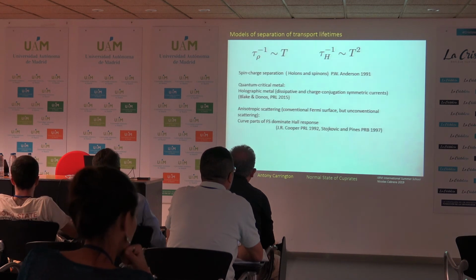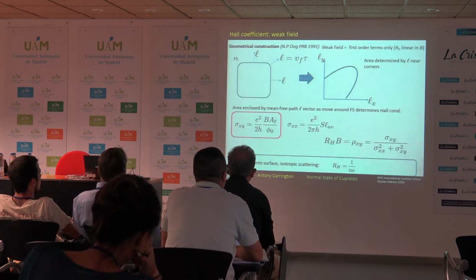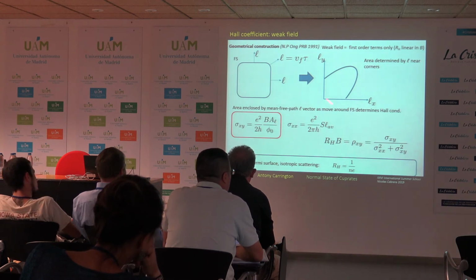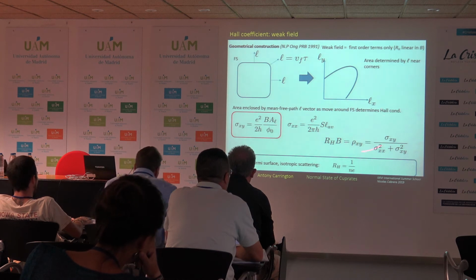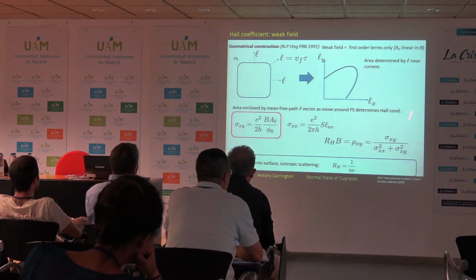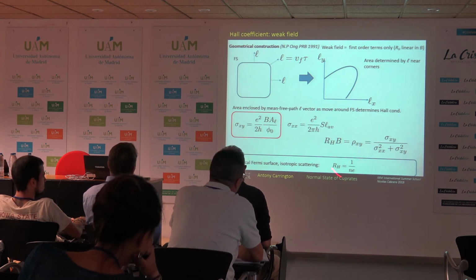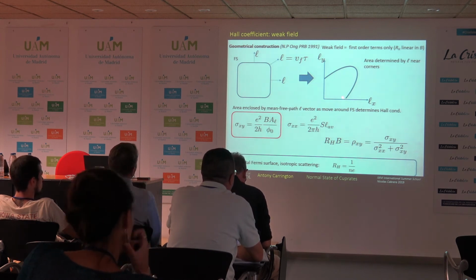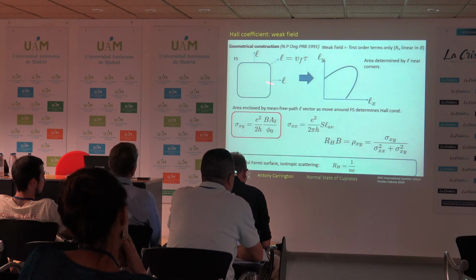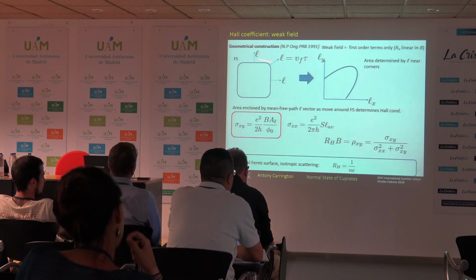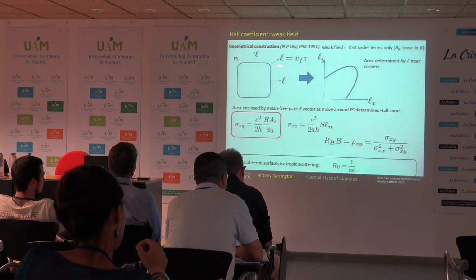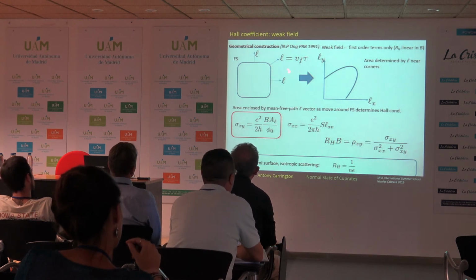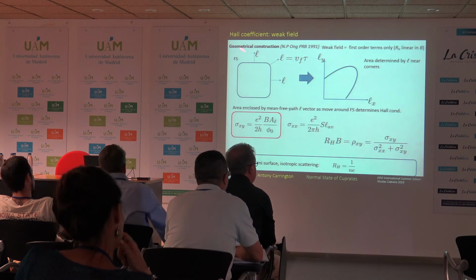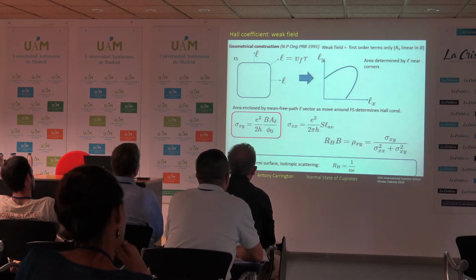So, where are we going here? Sorry. What this shows you then is that, in general, the Hall coefficient is not going to give you exactly 1 over ne. What it's going to give you is a number which could be larger or less than 1 over ne, and the degree to which it does so depends on how the mean free path varies as you go around the Fermi surface. And mostly the response is always going to be dominated by the regions where there's large curvature, so the corners in the Fermi surface like this.